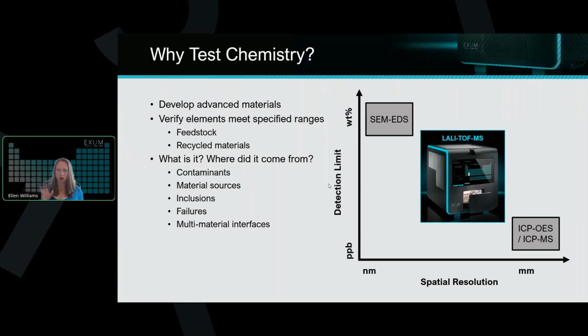And so really our technology, the LALI TOF-MS, which is embodied by the Massbox, fits in between these two different solutions and fills this gap. Because this is a mass spectrometry technique, we are able to measure trace elements down to the sub parts per million level, while at the same time creating elemental maps to show how elements change spatially down to micron level resolutions. So really complementary to those two pieces of equipment that you're likely already using or use external labs to use.